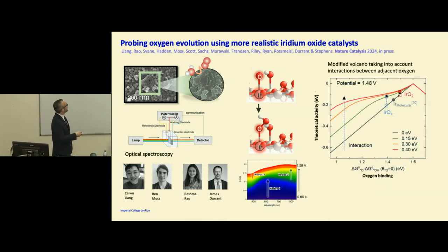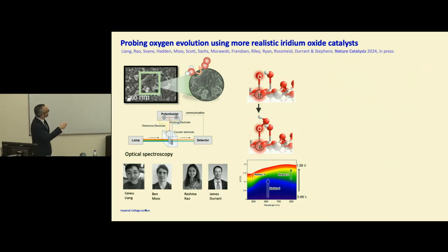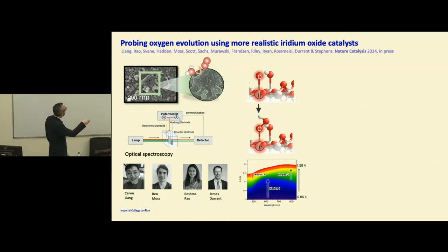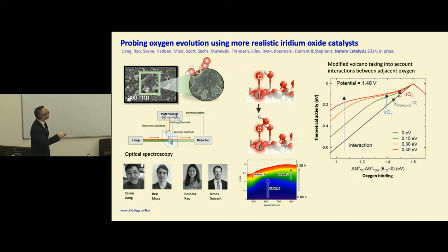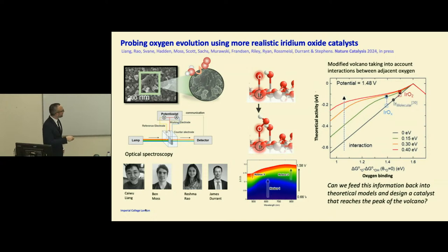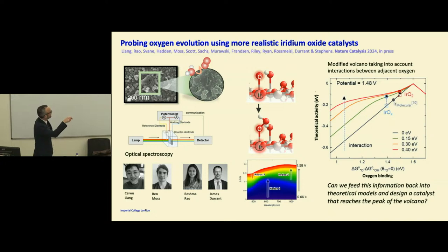What we found is that what really controls the performance is not just how strongly it binds, but how much these different intermediates interact with each other. They tend to repel each other a bit. And we could tell all that from looking at these spectra. It was really fascinating. And then we ended up making a new volcano. You can see the strong binding side of the volcano ended up becoming a lot flatter than before, which is very exciting. These are brand new results. Previously it was very difficult to benchmark the actual experiments against theoretical calculations, but now we're at the point where we can do that. Working with Lucas Garcia and Aron Walsh, what we would like to do is feed this information back into the theoretical models and design new catalysts to reach the peak of the volcano.